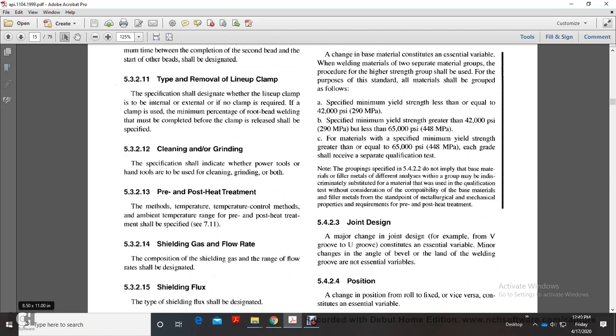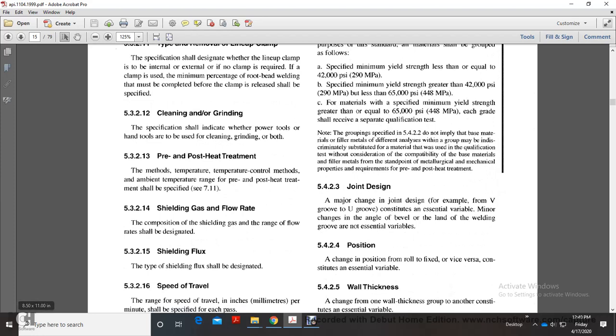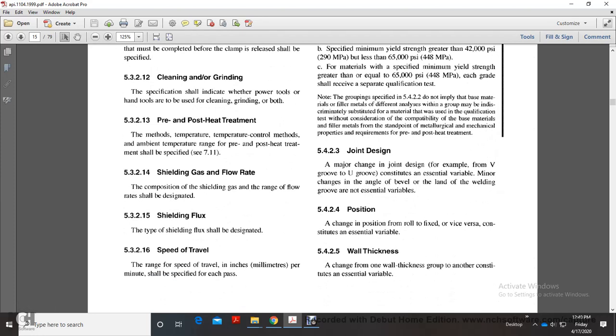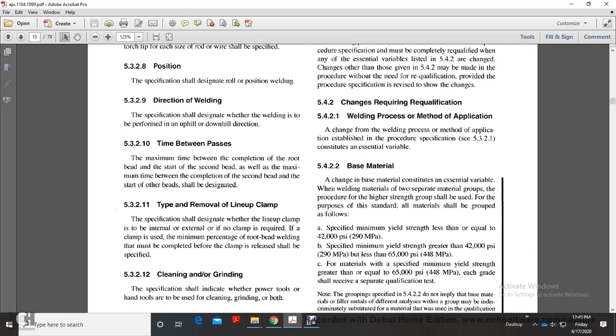5.3.2.14 Shield gas and flow rates. The composition of the shield gas and the range of flow rates shall be designated. 5.3.2.15 Shielding flux. The type of shielding flux shall be designated. 5.3.2.16 Speed of travel. The range of speed of travel in inches per minute shall be specified for each pass.